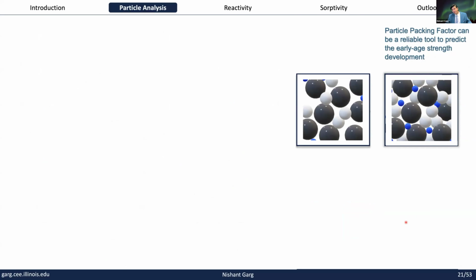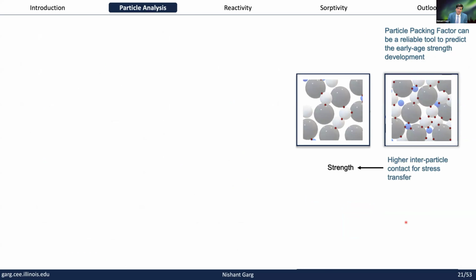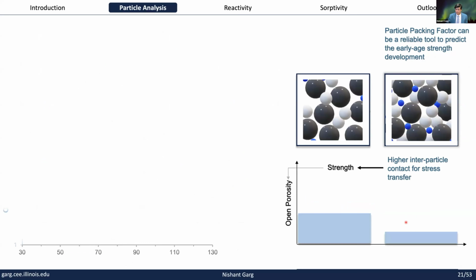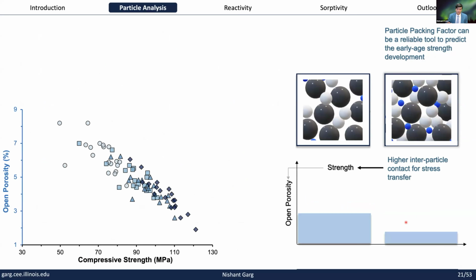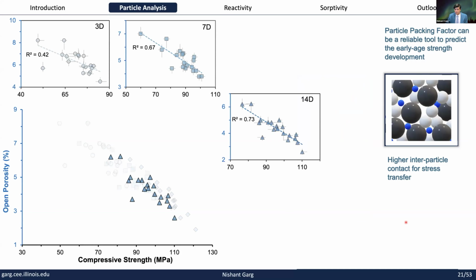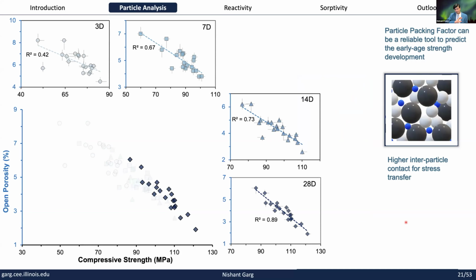Then we go one step further. We define something called the particle packing factor, because one of the things we have been interested in is designing ultra high performance concretes, which can have a strength of 3 to 4 times more than concrete. So if you want this kind of 120, 110 megapascal concrete, you really want low porosity. And for this low porosity, we find the particle packing really has to be done quite well. So we define a factor called the PPF, which can then single-handedly explain this improvement in the strength, and that can be used to design UHPC by just optimizing that PPF value.